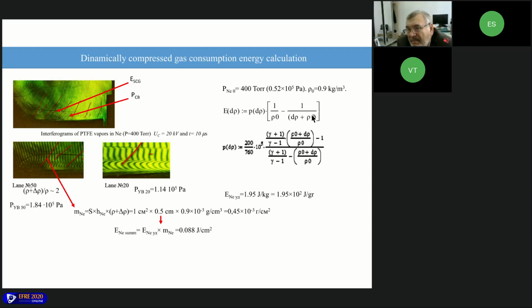And if we calculate the Hugoniot, and then calculate the energy, we determine that the energy is about 0.08 joule per square centimeter.